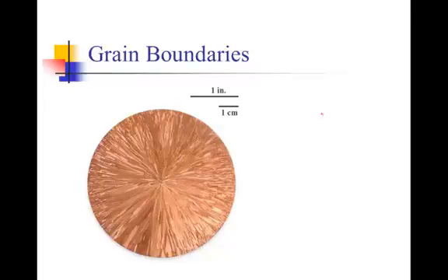And this is an example of a metallic material that's been cast as a liquid into a mold, and the crystal nuclei were having difficulty forming within the liquid, and the walls of the mold gave them a place where they could form a solid on top of another solid material, the wall of the mold being the second solid material. And so lots of crystal nuclei form along the walls of this mold.